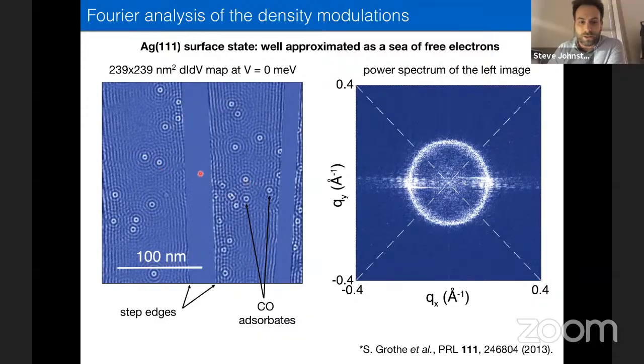What you're seeing here, these parts that are grayed out, are step edges, which have been removed from the data. Here is the carbon monoxide molecule, and here you see these rippling patterns. These are the Friedel oscillations, or the quasiparticle interference of the free electrons scattering off of these carbon monoxide molecules. If you take a Fourier transform of this image, you get a nice 2k_F image of the Fermi surface, right? This is the power spectrum, so this is telling you that the dominant wavelengths are really these 2k_F scattering vectors in the problem.